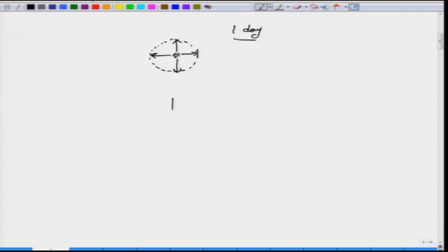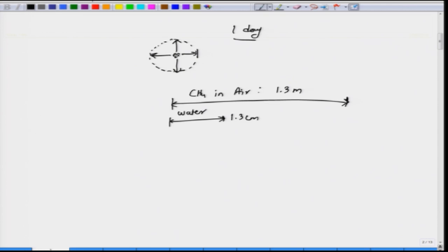So, in one day, if we consider diffusion of methane in air, this front would have progressed about 1.3 meter, whereas if you consider methane in water, this would have progressed only about 1.3 centimeter. These two are at a temperature of 298 Kelvin. But if you consider iron in copper, and that also at 900 degree centigrade, a much higher temperature, we will see that the diffusion front has progressed only around 65 micron with the diffusivity values that we listed earlier. So, the diffusion in solid is really very, very slow.